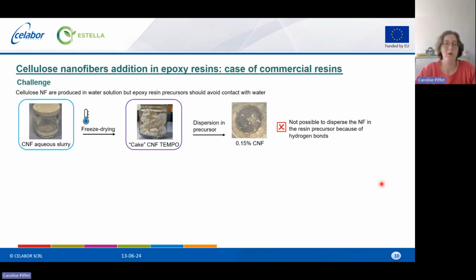Then, when we have our nanocellulose fibers in water, we have to face a challenge, because now we have to include this solution into the epoxy resins, but we have an aqueous medium, and the resin precursors are not compatible with the water to avoid degradation. So if we start with the simplest way, we dry the cellulose by freeze drying or another technique. We obtained a dried product of functionalized cellulose, and this can be included in the precursor of the resins.